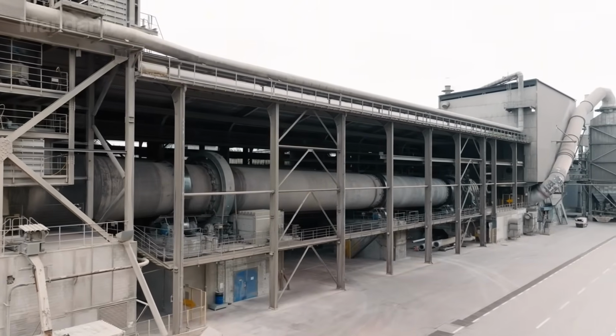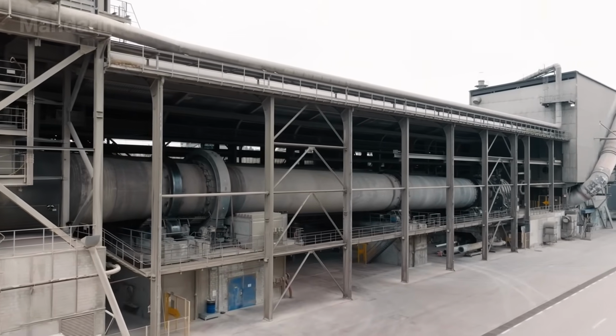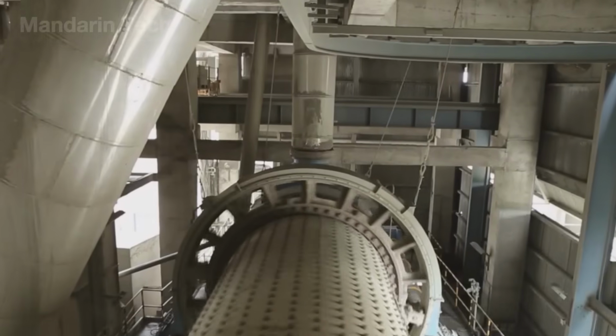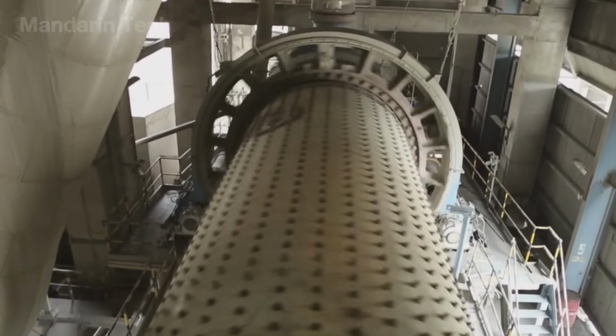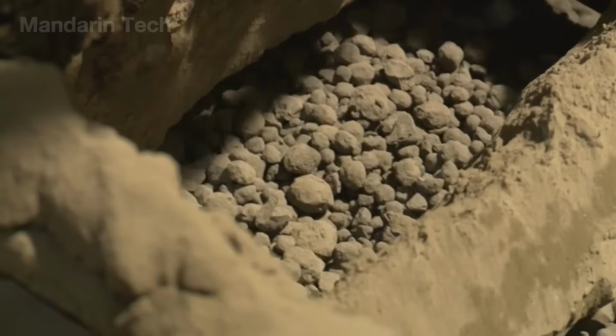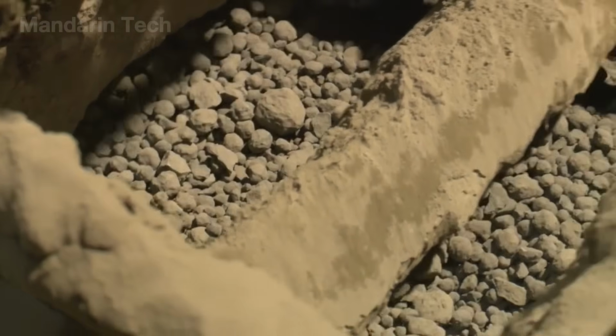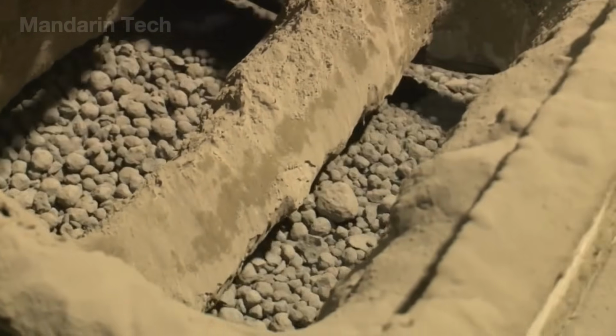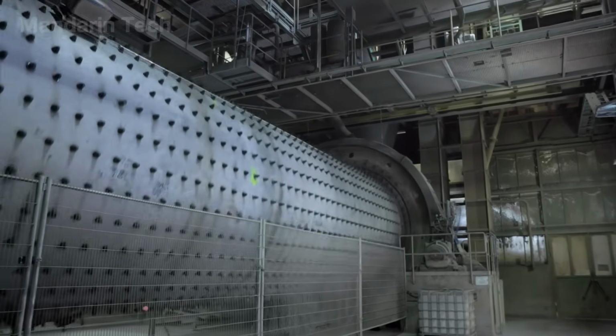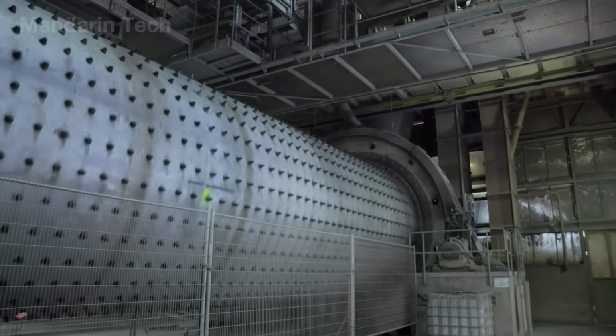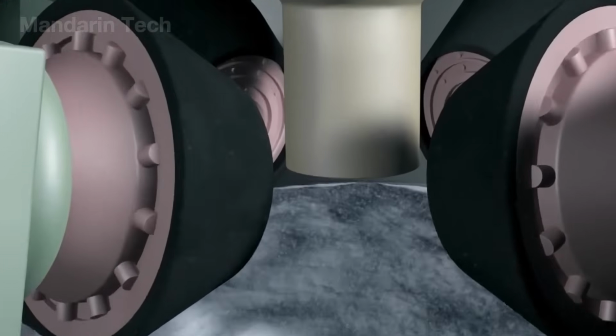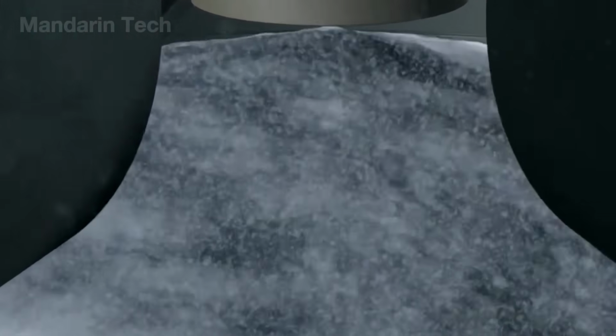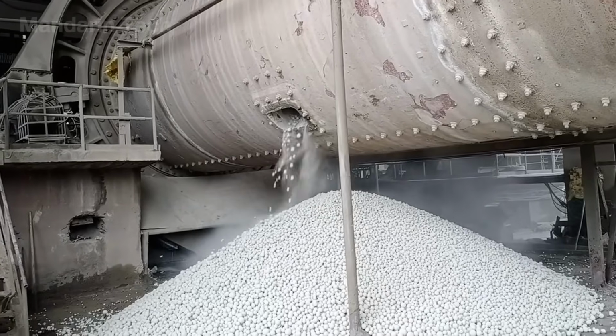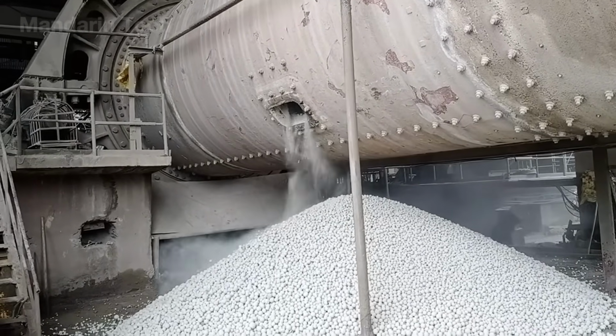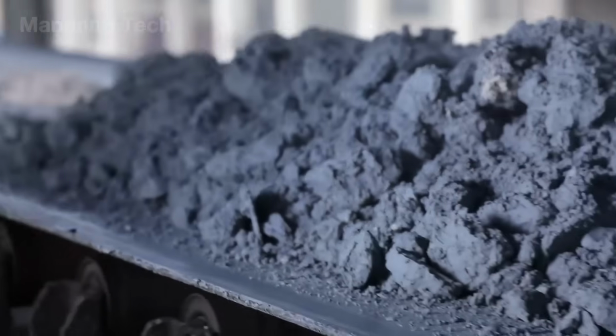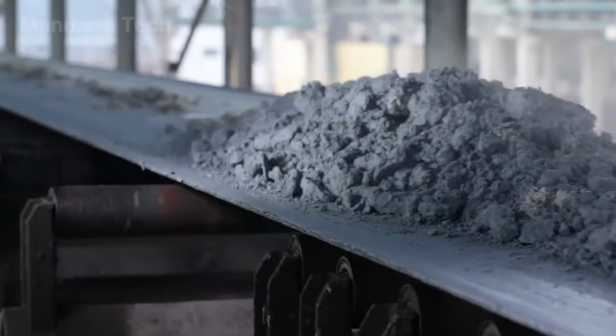The residual heat from the cooling process still clings to each clinker as they slide into the high-capacity grinding mill, processing several hundred tons per day. Here, the clinker mixes with about 3-5% gypsum and mineral additives, such as fly ash or ground granulated blast furnace slag. Under continuous pressure and friction from steel balls or rotating rollers, the mixture gradually breaks down into fine cement powder with a fineness of around 4,500 cm²/g.